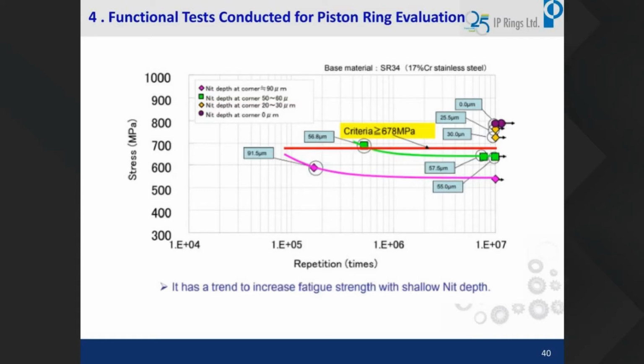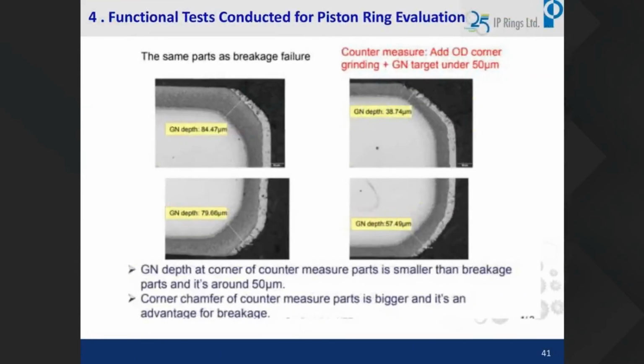Whereas when we reduce the diffused, nitrided thickness to around 30 or so, it is meeting the requirements. So what we did is we reduced the diffusion time from 7.5 hours to 4 hours. And we also introduced one additional process, called corner grinding. We removed some of the nitrided portion from the corners, and after that we coated.